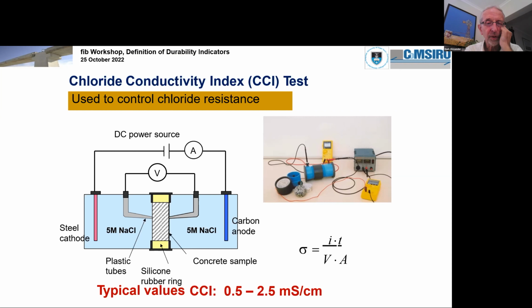But what we did here was that we used a specimen in which we saturated the pore solution with a sodium chloride solution so as to eliminate the influence of the pore structure, as it were, and we were able to pick up the intrinsic characteristics of the material itself. So this is a test. Again, you have to condition the specimen, but once the test is in the rig, it takes no longer than about 10 or 20 seconds to get a result. So it's a very rapid test, and the values come out in millisiemens per centimeter, typically between 0.5 and 2.5 millisiemens per centimeter, which represents quite a large range of chloride resistance of the concrete.